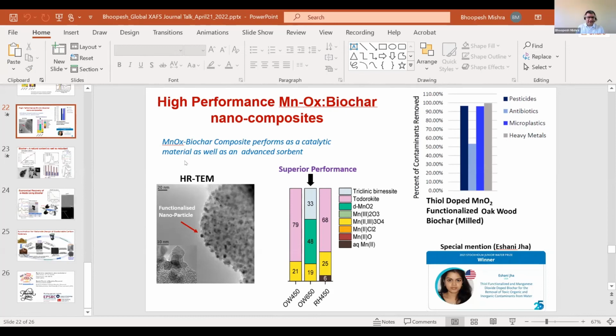Yeah, so what I was saying is that the idea was to develop this for capturing mercury from effluent gases and flue gases and so on, because mercury is usually in the mercury zero state. So the idea was that manganese oxides will oxidize mercury to mercury oxide, and then if there are thiols functionalized on these sites, then we also know from my previous research that this mercury can be converted into mercury sulfides, which is very stable. So that would be a very potent way to first capture mercury zero and then oxidatively transform that into mercury oxide, and then eventually convert them into more stable mercury sulfide or mercury thiol forms. So that was the initial intent, which we did succeed in partially or to an extent.